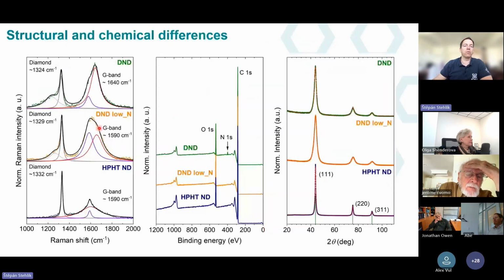Okay, so let's compare. Also, let's briefly go through some fundamental physicochemical characterization. So the Raman spectra, you can see that this low nitrogen DND is indeed a bit different than the DND material. It has a slightly less shifted and slightly narrower diamond peak. And also there is some difference in the G band, where we see a higher contribution of this graphitic-like band or component, and lower contribution of this 1590 band, which is associated probably with some isolated sp2 defect, and this one is very prominent in DNDs.